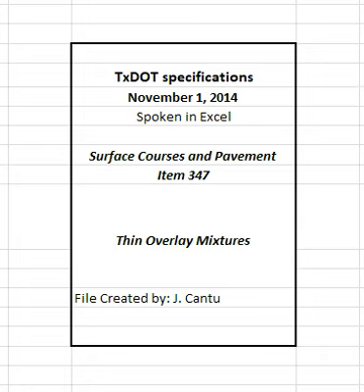4.4.1 Design requirements. The contractor may design the mixture using a Texas gyratory compactor, TGC, or a Superpave gyratory compactor, SGC, unless otherwise shown on the plans. Use the typical weight design example given in Tex-204-F, Part I, when using a TGC. Use the Superpave mixture design procedure provided in Tex-204-F, Part 4, when using a SGC. Design the mixture to meet the requirements listed in Tables 1, 2, 3, 6, and 7.